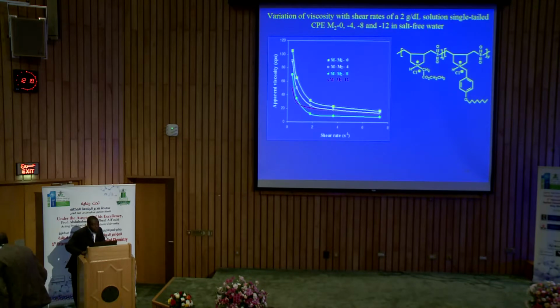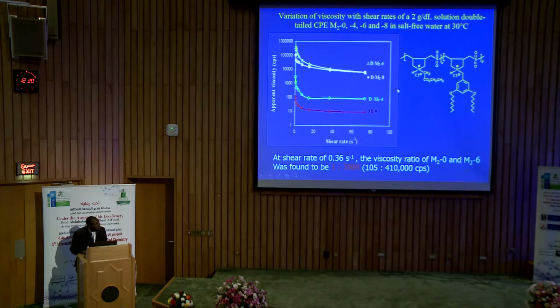Now, this is a typical viscosity behavior. For the green one, the M0 means we have no hydrophobe. So the viscosity of mono, which is M2 here, is the lowest, which means that what takes place in aqueous solution is intramolecular association. So with the mono, there is no increase in viscosity. That tells us that what happened is mainly intramolecular association. Then we try the double tail. The double tail gives us a tremendous increase in viscosity, this is the mono, and this is double tail. The viscosity is very high to the extent that the ratio is 1 to 3,905.